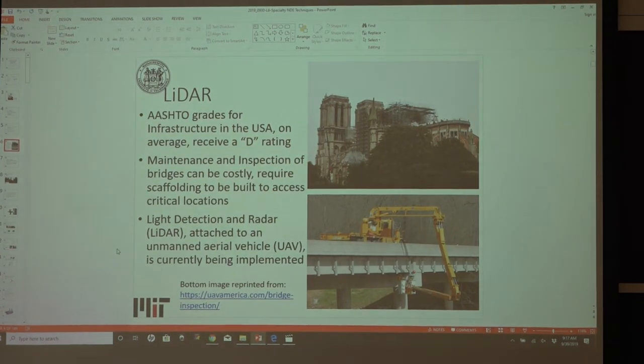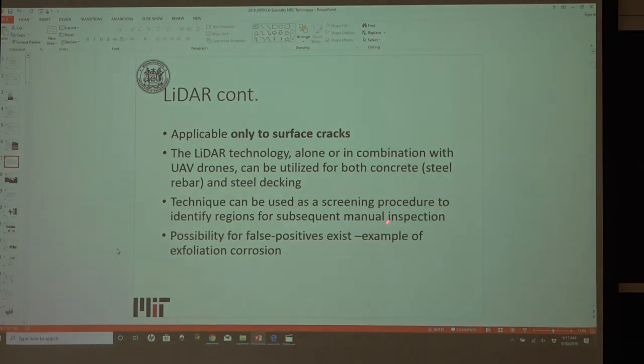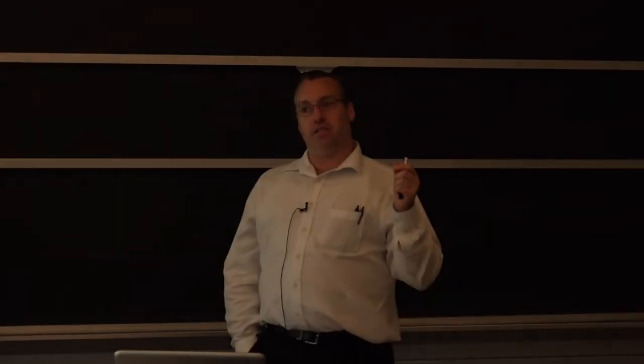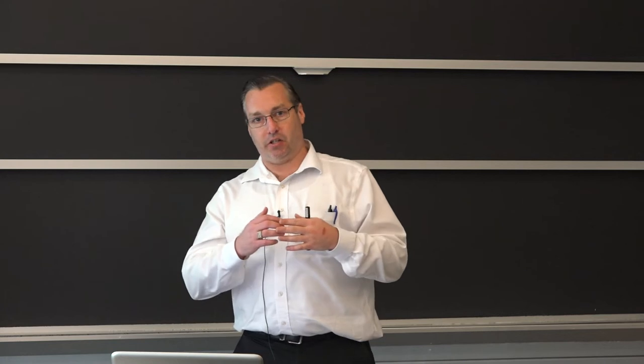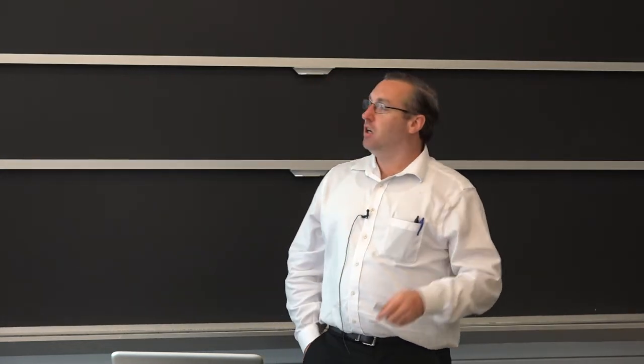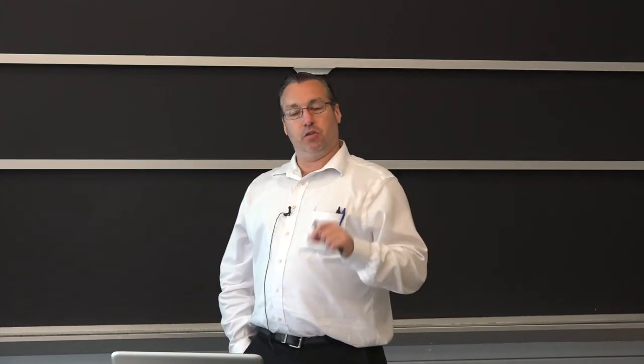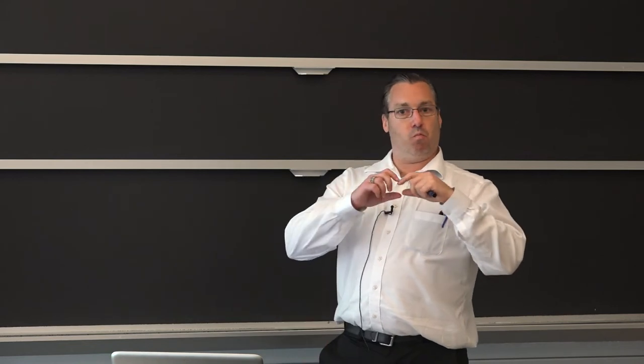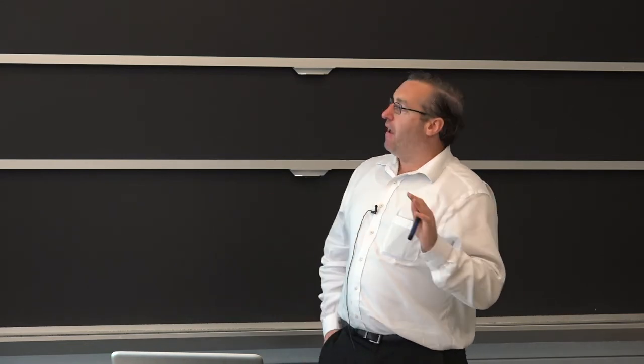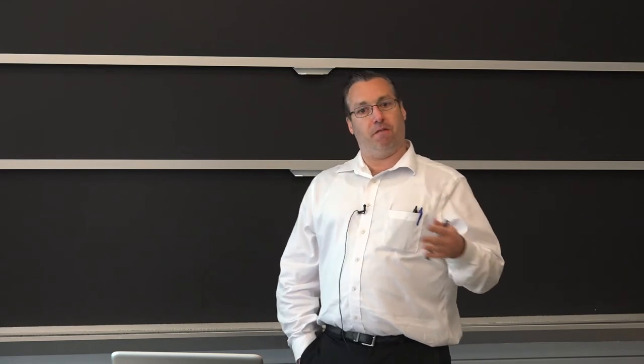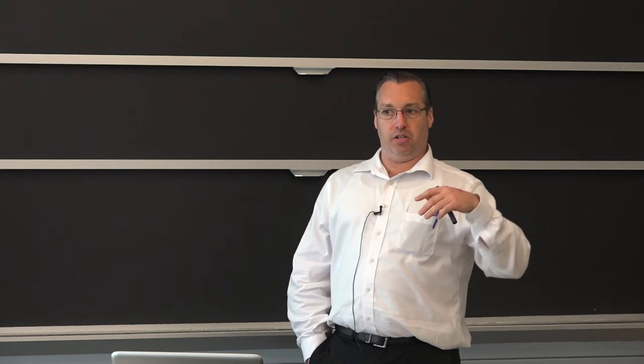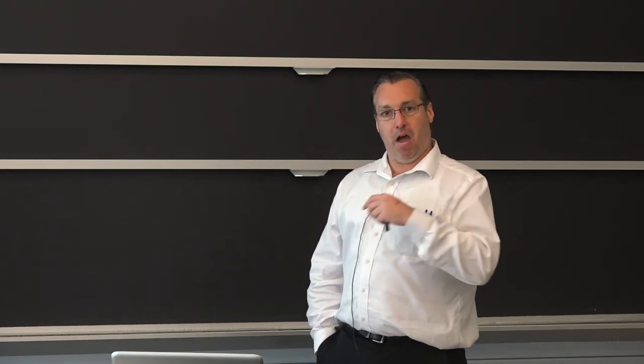One of the concerns with performing that type of inspection, however, is that it is only applicable to surface cracks. This is also related to inspection of thick concrete structures. So if there is a weld defect on the underside — whether it's a butt weld or other joint connection — and if there was a lack of fusion or other welding flaw, this technique would not be appropriate to detect that crack. There are also limits of detection with respect to whether a crack has begun to propagate. But in terms of accelerating the speed at which you can inspect bridges, it is much faster than bringing heavy equipment onto the site, closing down areas, and having a person do a manual inspection.